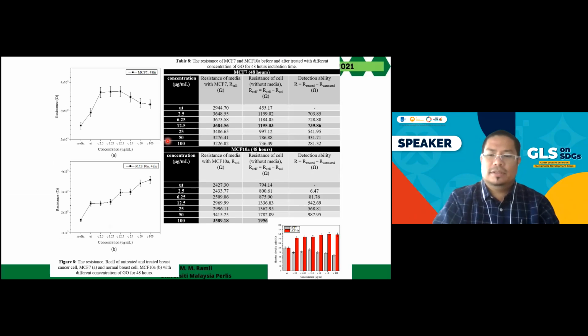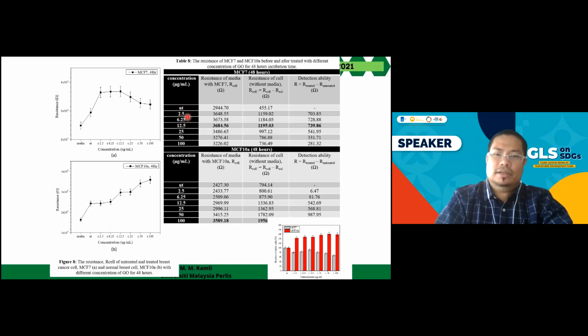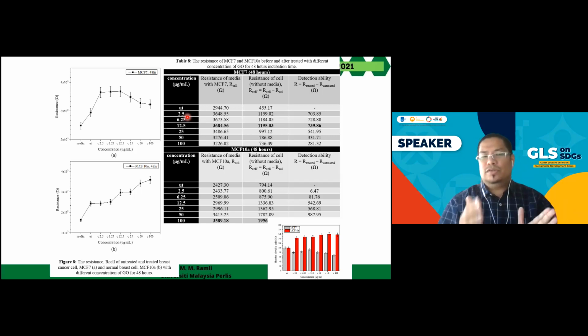We also did the electrical characterization. I just take one example because of the time constraint. We have the untreated sample, meaning MCF7 only, the breast cancer cell only. Then we vary the concentration at 24 hours treatment and 48 hours treatment. For each treatment time and each concentration, we measure the resistance of those cancer cells. We use IDE, interdigitated electrodes. We drop our graphene oxide inside the breast cancer cells in a petri dish and leave it for 24 and 48 hours. After that, we take our samples and drop them on top of our interdigitated electrode, the device that we fabricate in our lab, and then we measure the resistance.